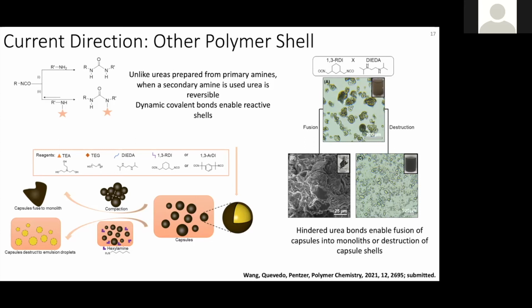And these are just for oil and oil emulsions. She's done it for a number of different monomers. But what she observed was when there was ionic liquid in the core, she actually could not isolate stable capsules. And we attribute this again to the plasticization of the shell with the ionic liquid, which provides a more polar environment and really decreases the temperature for that reverse reaction. And we've done variable temperature NMR to show all of these things.